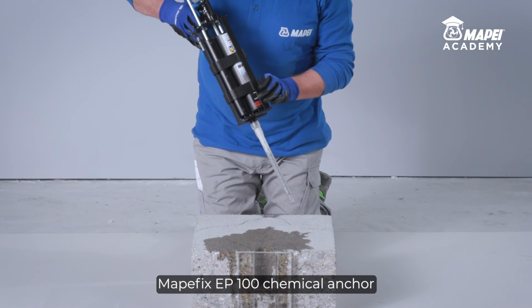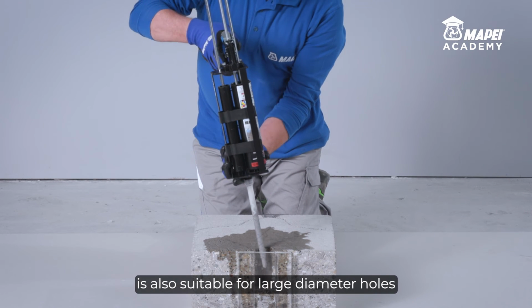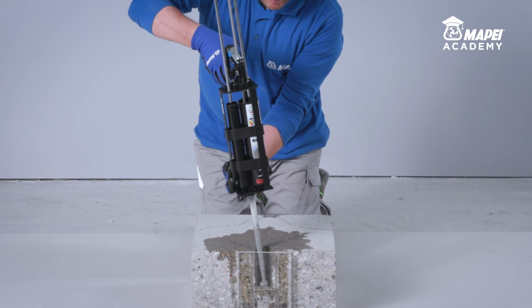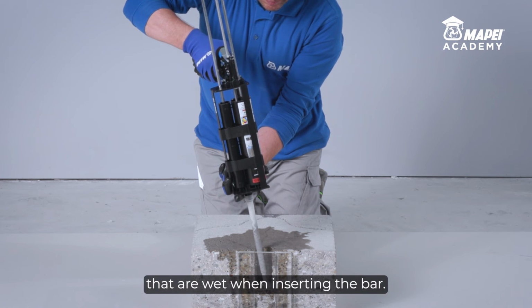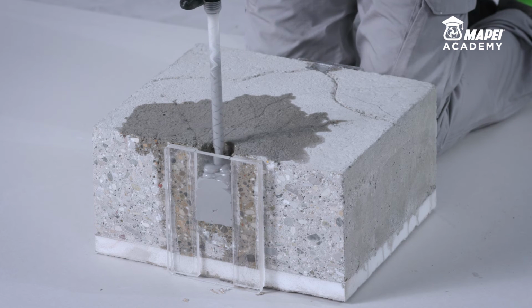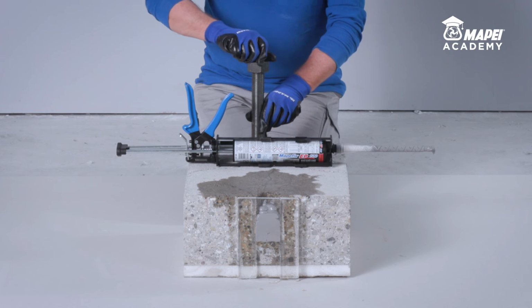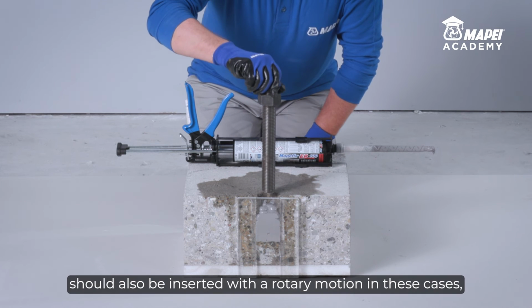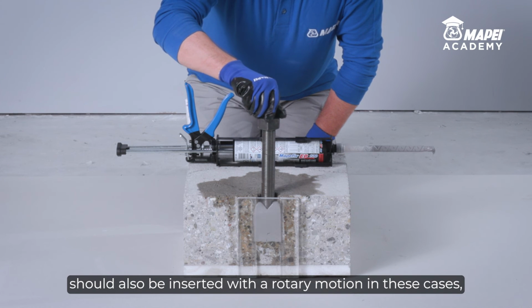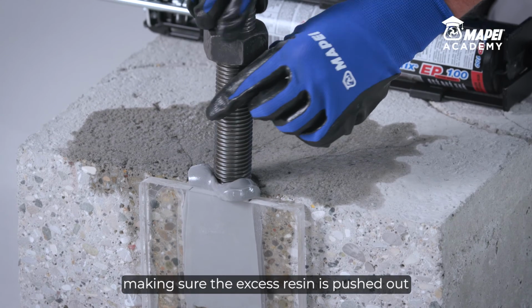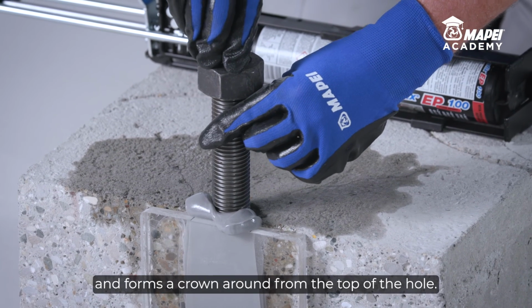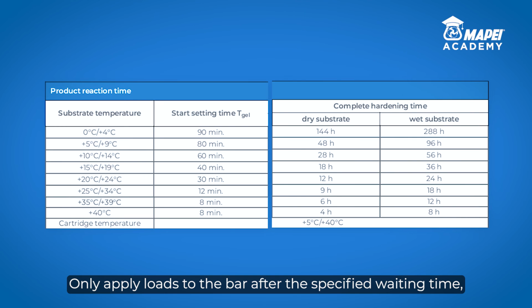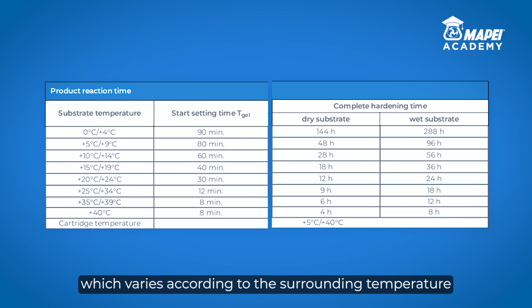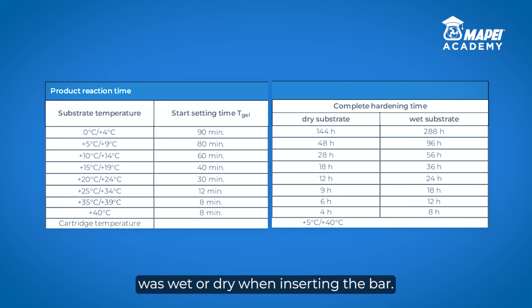Mapefix EP100 chemical anchor is also suitable for large diameter holes made using a diamond cutter, and for holes that are wet when inserting the bar. The clean, rust-free steel bar should also be inserted with a rotary motion in these cases, making sure the excess resin is pushed out and forms a crown around the top of the hole. Only apply loads to the bar after the specified waiting time, which varies according to the surrounding temperature and whether the hole was wet or dry when inserting the bar.